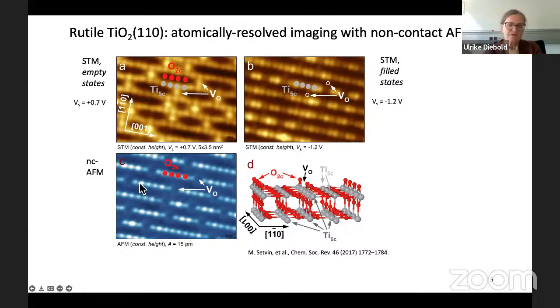you see oxygen vacancies. This is a non-contact AFM image. You see these rows of oxygen atoms, and some are missing. You see these vacancies. And the way we do these experiments, we can look at the oxygen atoms, but we can also look at the electronic structure. This, for example, would be excess electrons that are trapped in the near surface region. At the titanium sites, doesn't matter where, but things like this we do quite a bit.